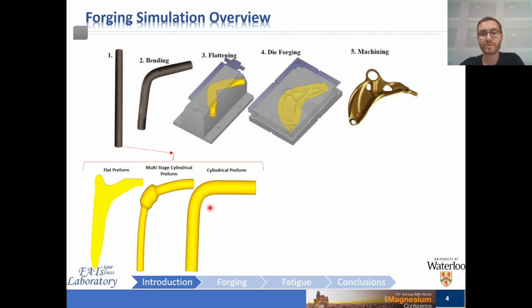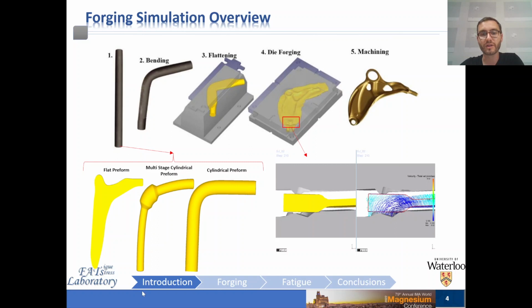We optimized the process in several ways. The forging temperature, as well as the strain rate, were both investigated. Furthermore, we took mass optimization very seriously, and we took it a step further by intelligently developing the component geometry, which was redesigned specifically for forging of magnesium. We didn't just recycle the geometry of an aluminum component.